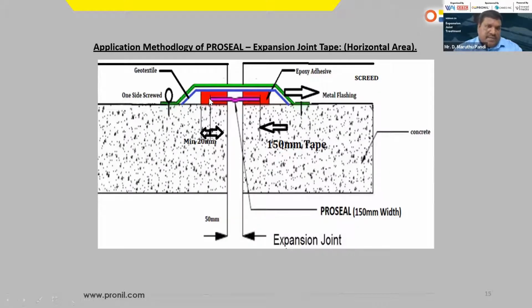Then minimum 20 mm is required to fix the adhesive from the end of the tape to the substrate. Then only it will have a better bonding on the substrate, 4 Newton per mm square while doing a pull-out strength. Considering this as a podium slab, I'm going to put a geotextile on top of this expansion joint tape and the epoxy. This will protect against damage from the further grading or further plates which will be placed on top of the tape.